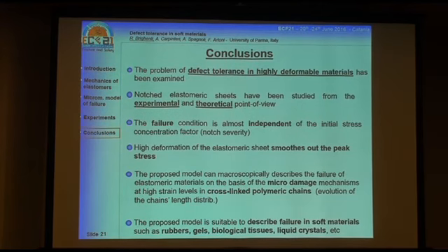So let's move to some conclusions. We have considered the problem of defect tolerance in highly deformable materials, such as rubbers and polymers. We have tried to verify the capability of this material to withstand defects, both from an experimental and theoretical point of view. And we developed a model based on the rubber elasticity theory that can explain how locally the material fails under large strain. As we have seen, the ability of this material is to smooth out the peak stress, and so the initial defect loses its character to decrease the strength of the material.